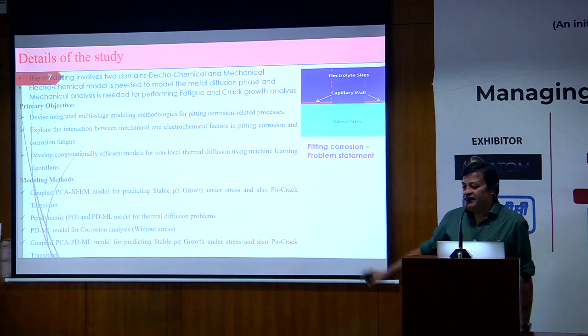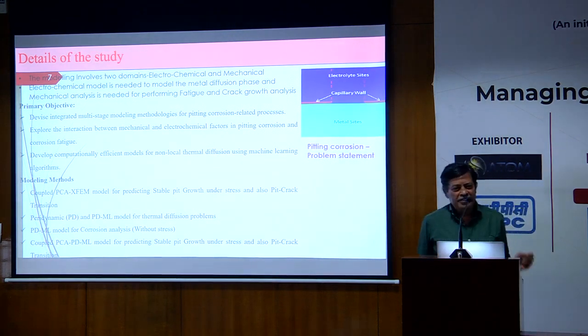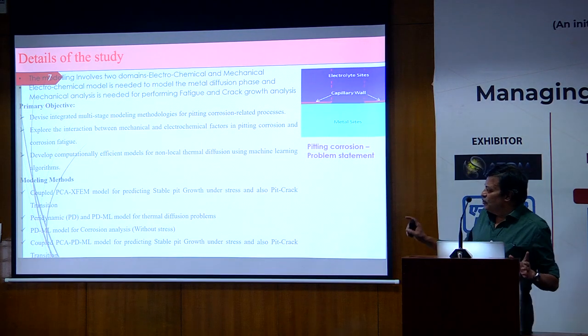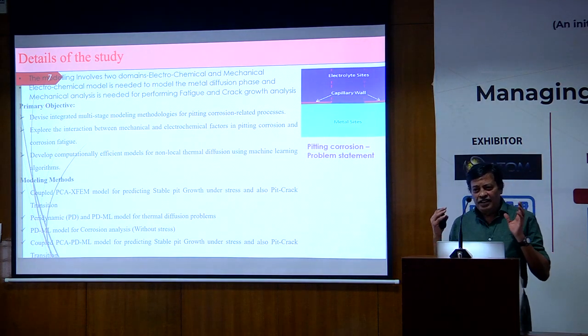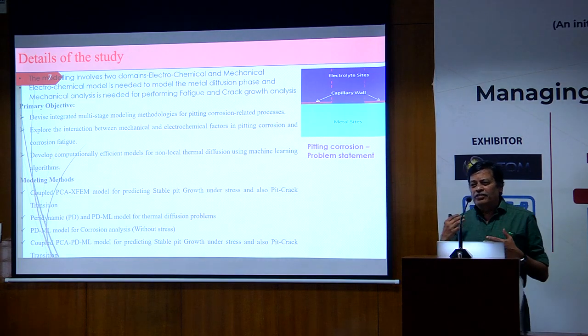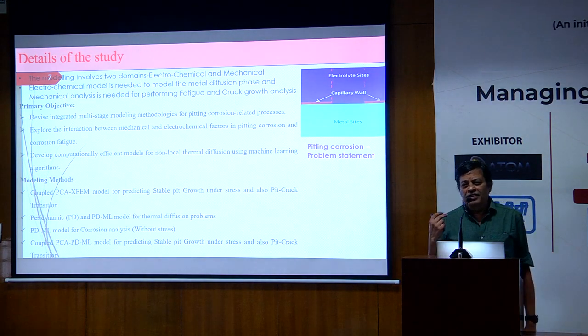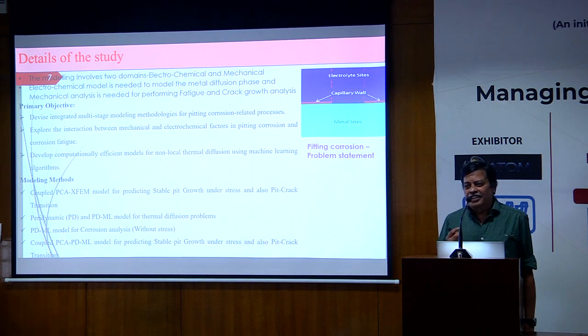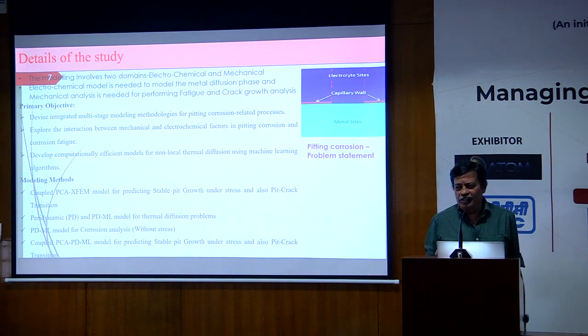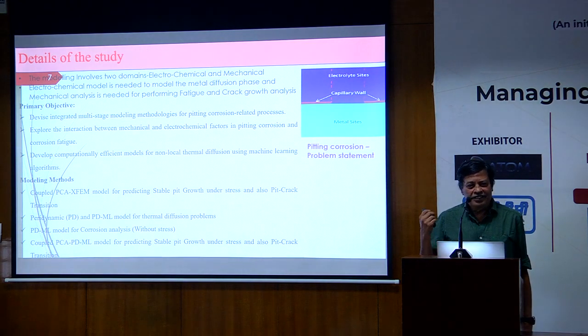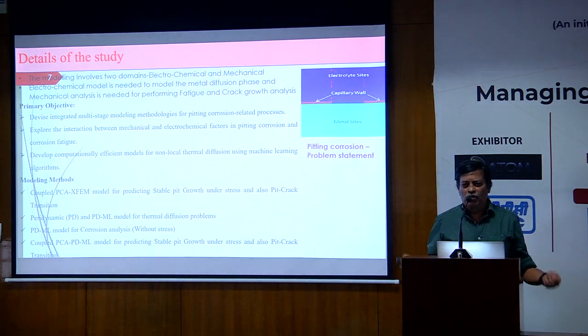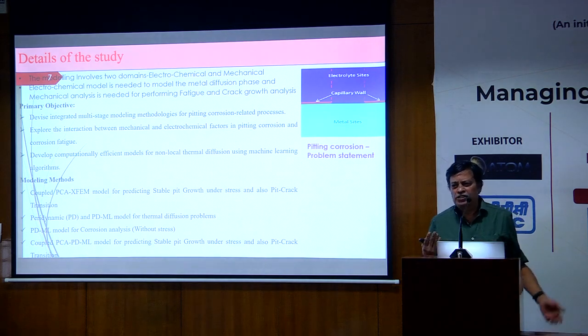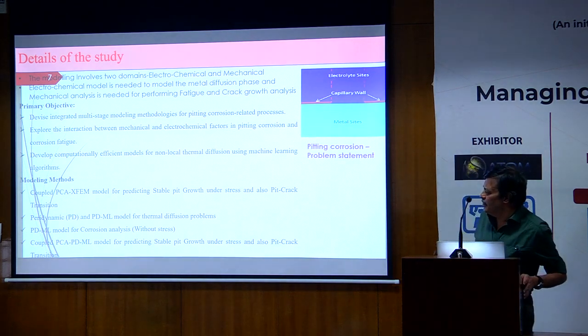Yesterday. And we extended it to what is called the peridynamic model, which is an integral model. And we have shown how we can use that integral model. Two important phenomena in pitting corrosion are the corrosion process, the oxidation process, and the diffusion process. And both are governed by what is called Faraday's law and Fick's law. And we have modeled that chemically using extended FEM. And mechanically, we can model with the conventional FEM. We couple these things together. That's the whole philosophy that we use.